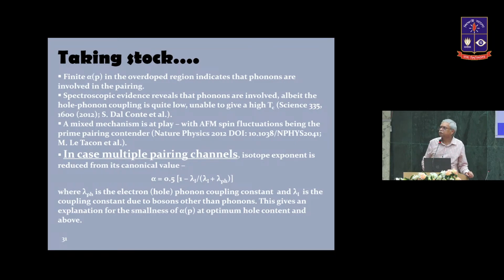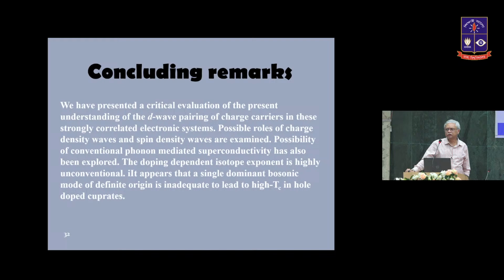So the conclusion we can draw is that in copper oxide superconductors, it will not be very productive to expect that a single type of boson is playing the role to bring about the Cooper pairing. We think the situation is mixed. Multiple degrees of freedom are coupled with electronic degrees of freedom. For example, the spin waves are there. Short-range antiferromagnetic order persists over quite a significant region of the electronic phase diagram. These fluctuations, together with phonons, lead to the superconducting pairing in high TC cuprates.